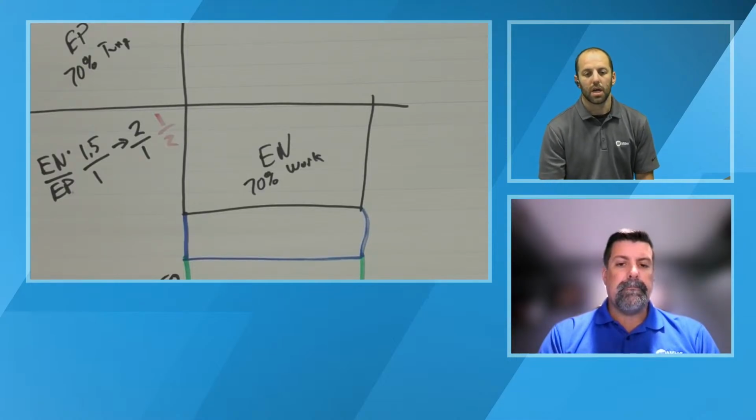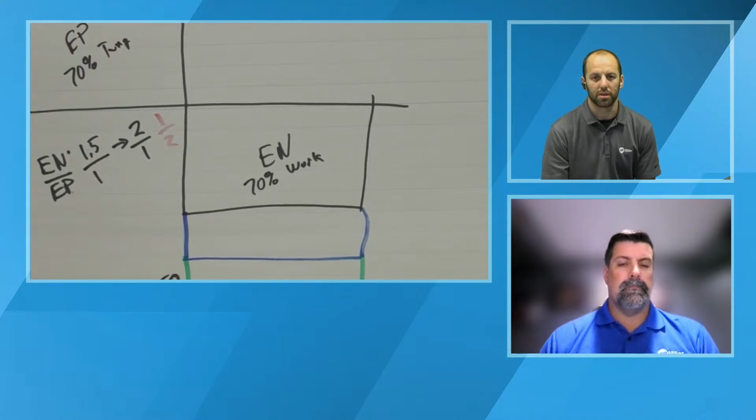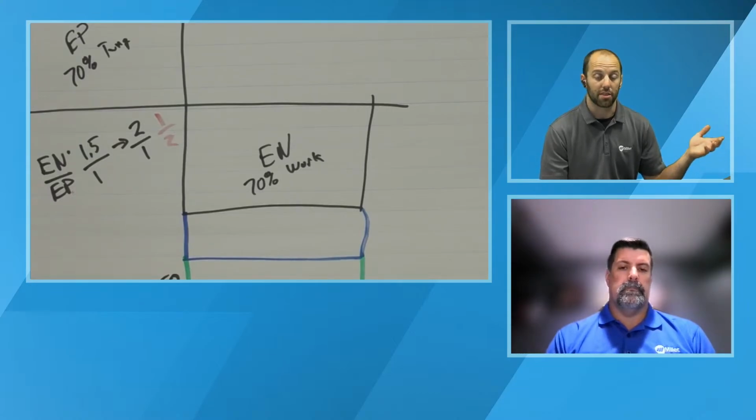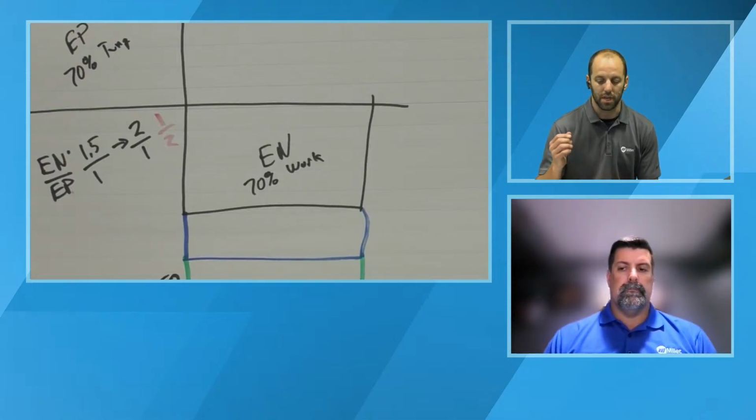Sure. That's a great question, and we actually get that quite a bit. In regards to balling the tungsten or pre-balling the tungsten, there are applications where you may want to pre-ball it. As we talked about last week, the balance setting showed that we have the ball setting at 30%. If we go into balance and turn the range all the way down, that gives us a lot of heat on the tungsten to pre-ball it.